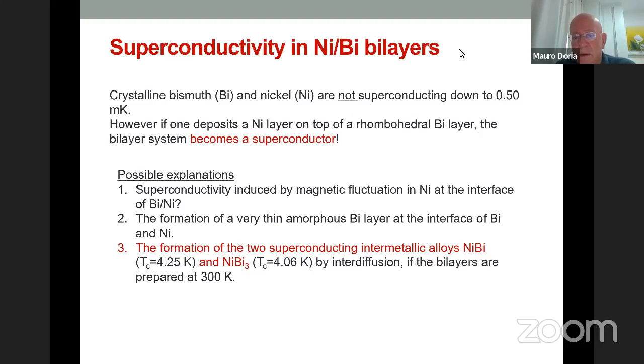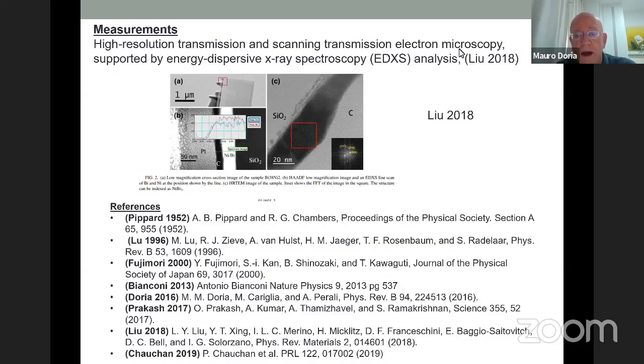But at the end, what was found is that when you put these two elements together, you make two intermetallic alloys, which is nickel bismuth and nickel bismuth 3, which have critical temperature of 4 Kelvin. When they interdiffuse one into the other, you form these two elements, and so that's the answer to the problem. And this was found by Liu and collaborators. They did very nice high resolution transmission and scanning transmission electron microscopy, X-ray spectroscopy analysis. And by 2018, they verified that there are new elements in this interface. So I recommend the reading of some of these papers here.